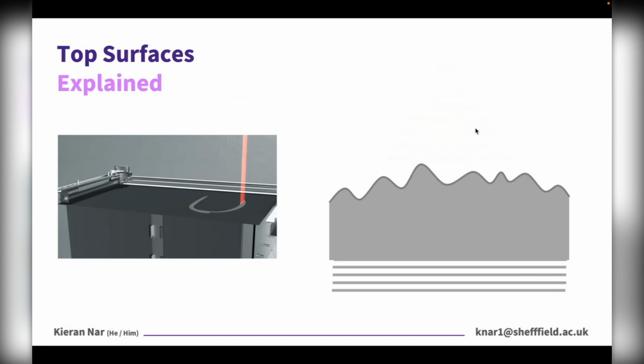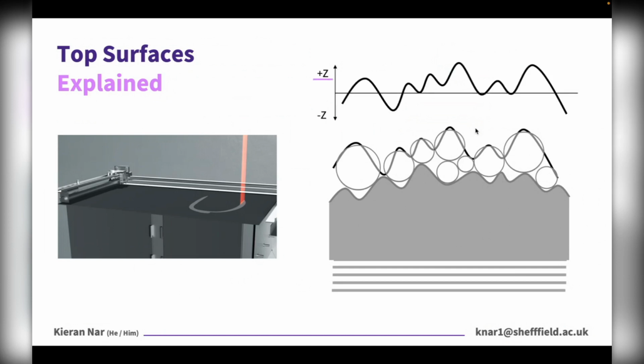Though one part of the build process that we weren't able to grasp from this GIF was that upon the final build layer being sintered, it's common practice to then consecutively deposit numerous more blank powder layers, otherwise known as finish layers, on top of the parts produced. And on our machine, for example, it's default practice to deposit 40 additional finish layers on top of the parts. And the reason for this is to bury all the parts produced to ensure that they subsequently cool evenly, to prevent them from warping. Though, as you can see from this illustration, this is also the mechanism that I thought might be the reason why resultant top surfaces tended to be asperity peak dominated.